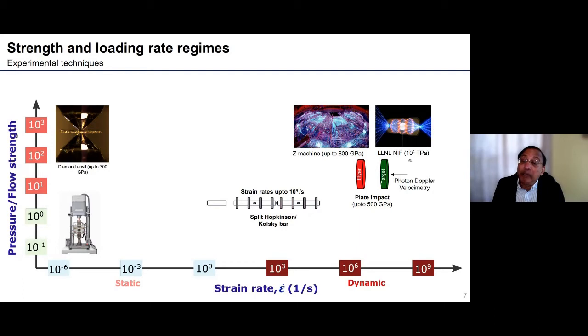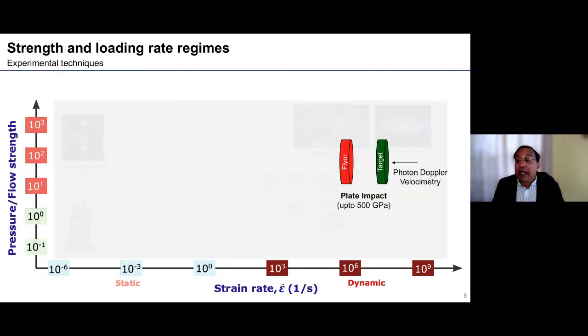We are going to look at the plate impact technique, with which we can generate high pressures. Primarily this technique has been used for studying the equation of state of materials, with limited studies on the strength behavior of materials, which we'll discuss in a few minutes. In the normal plate impact technique, one uses PDV, photon Doppler velocimetry, or VISAR, to measure the response either at the free surface or at the interface with the window, to understand the evolution of the normal velocity profile from which one can obtain the equation of state.